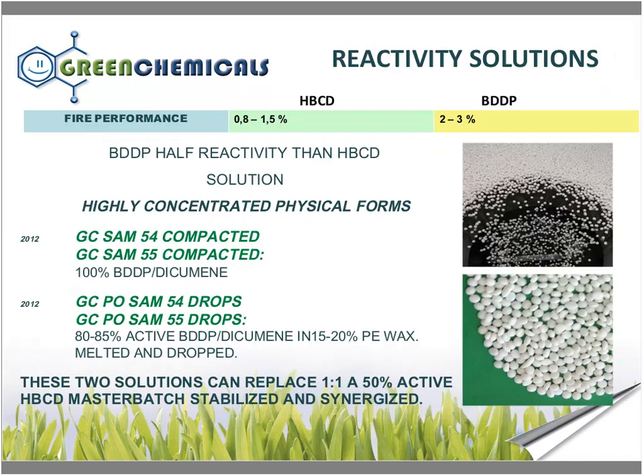Now, the activity. As Ethel has shown you, we can consider BDDP to have half the activity of HBCD. Considering that in XPS almost the whole market uses a 50% active HBCD master batch, the point was to concentrate BDDP as much as possible in a granular form. The first experience we had was obtained by compacting BDDP and dicumene together, obtaining a granular product, as in the small picture. But most XPS producers still cannot use it because of the presence of fines, which creates problems in the feeding system.